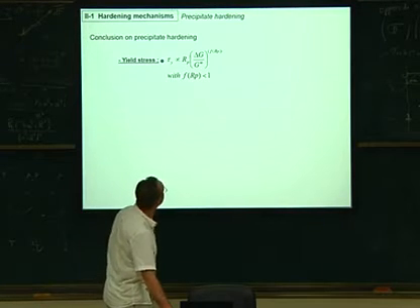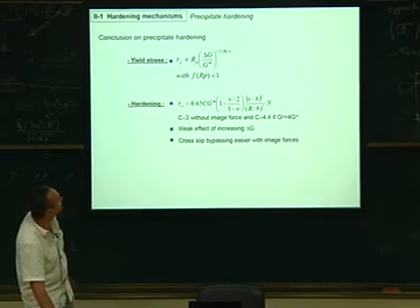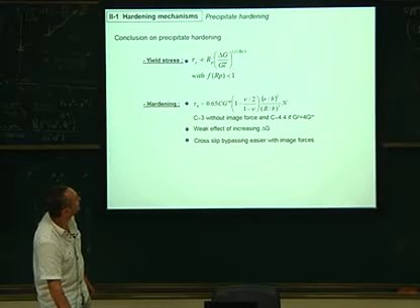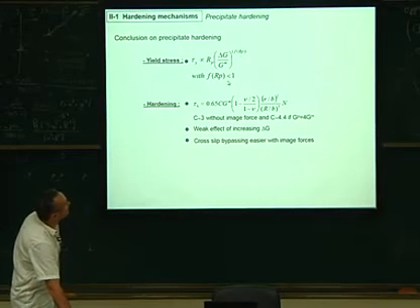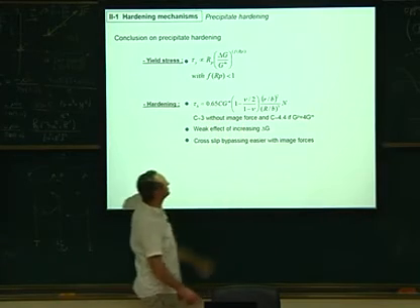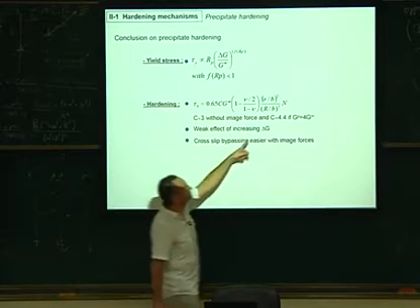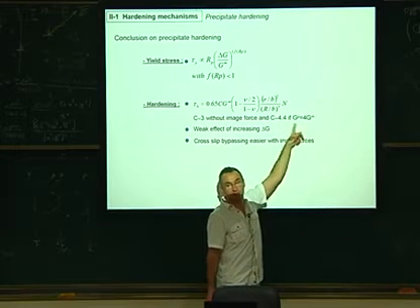Yeah. So the first thing is that the yield stress, we found that it's evolving like that, depending on the change of elastic moduli, like this, compared to the matrix. So this is a dimensionless number, where the power here is lower than 1. And the hardening is following the Fisher equation, as I showed you just before, with a C coefficient, which is not the same, depending on the ratio between the particle and the matrix moduli.